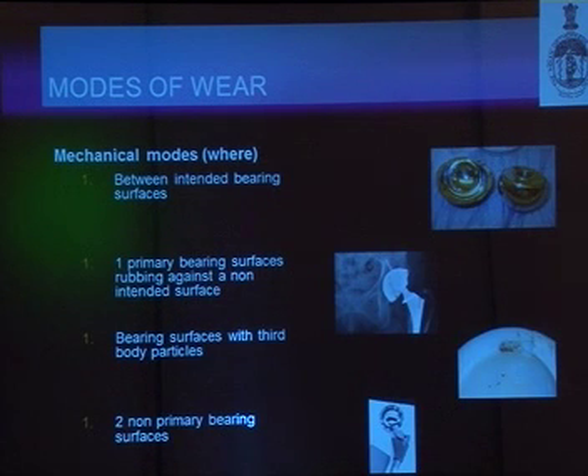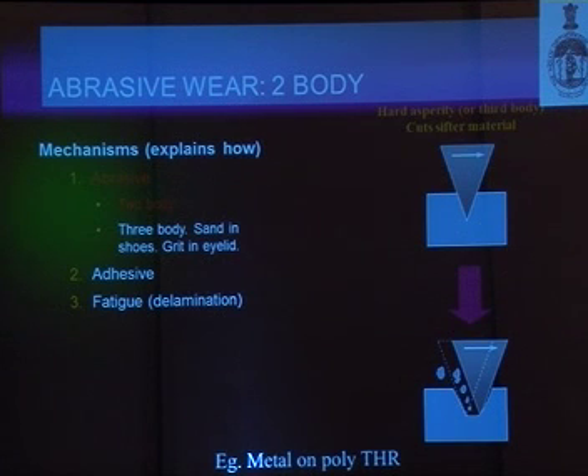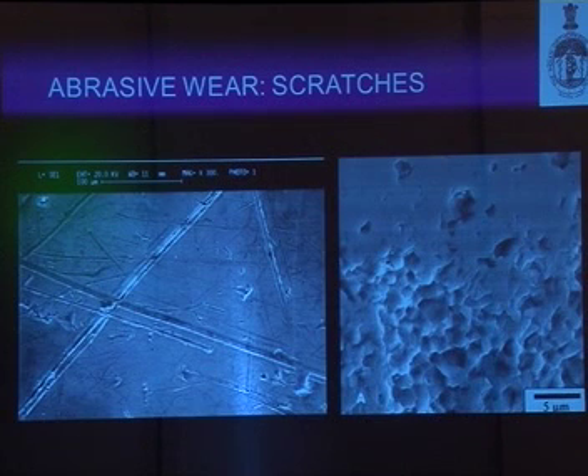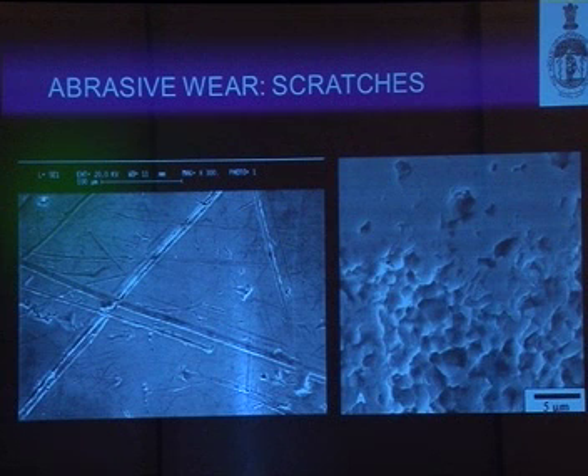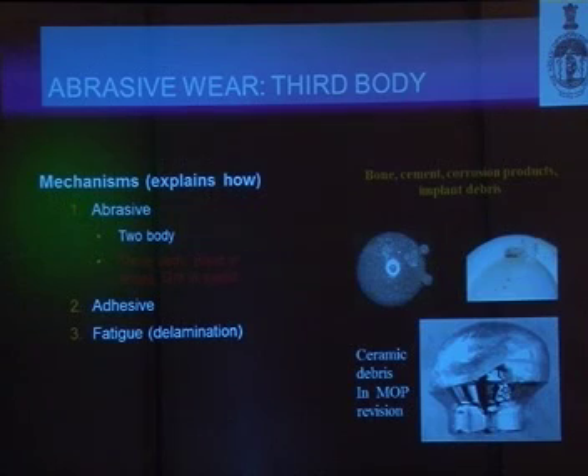So the modes are mechanical modes, which could be between the intended bearing surfaces, could be between a bearing surface and a non-intended surface, could be with a third body particle I just mentioned, or between two non-primary bearing surfaces. So abrasive wear is normally between two surfaces or two bodies. We talked about adhesive and fatigue. Normally it results from scratches to the surface, where it could be on ceramic, or could be on metal and poly.